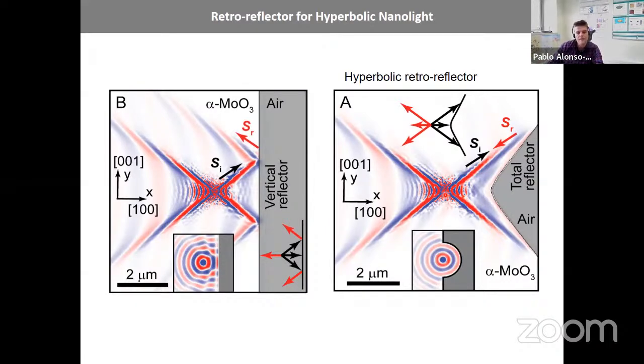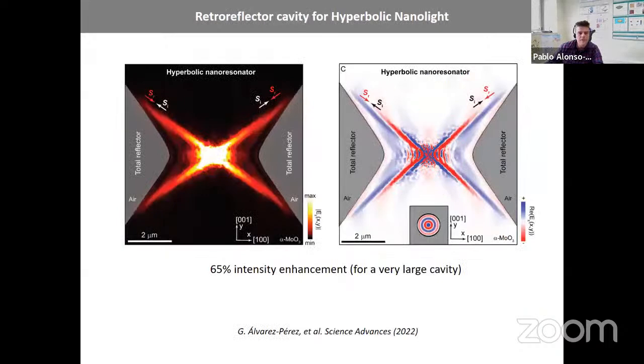Okay, how can we make a cavity? By putting two of them on the two sides. And then these are the simulations as well, for the intensity, and for the field, sorry, and for the real part of the field. And then you can see that this light, this hyperbolic nanolight, excited in this material, they go to these reflectors and they come back to it.